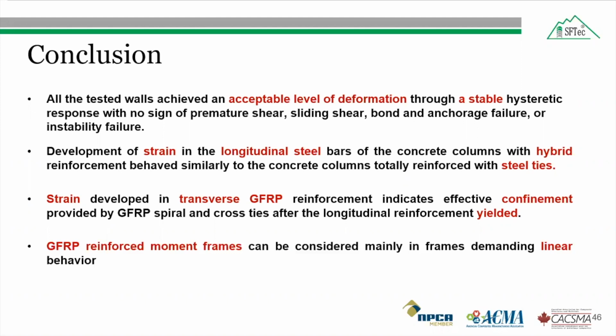The linear behavior of GFRP bars with considerable strain capacity puts it in a position to be considered mainly in frames demanding linear behavior and frames with low to intermediate story level. As I showed, if the aspect ratio is low, then the GFRP performs better. Further, the soft story phenomena in GFRP reinforced moment frames can be avoided by providing higher stiffness to the columns or vertical members, which can be achieved by using hybrid reinforcement with steel as vertical members, which was shown in the research on the shear walls and the hybrid reinforced concrete columns.